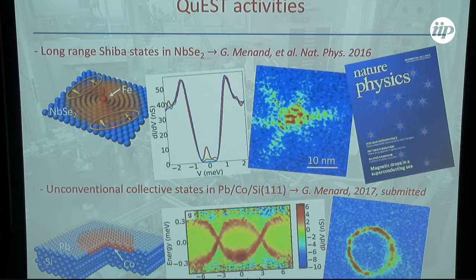The destructive interference between Cooper pairs and this magnetic moment leads to so-called Yu-Shiba-Rusinov states, which are bound states appearing as two peaks inside the superconducting gap. So this is the superconducting gap of niobium diselenide, and inside it you have two peaks, which appear symmetrically with respect to the Fermi energy; they reflect one bound state, which is a spin polarized state.